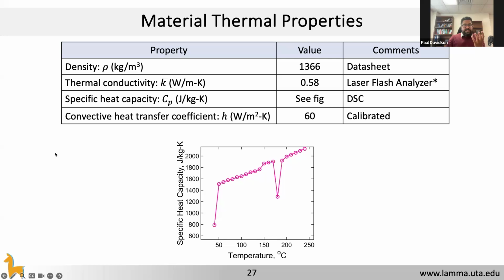So we first measured the material properties of the tape itself. We got the density from the data sheet. We did a thermal conductivity test using a laser flash analyzer. We did specific heat capacity using DSC. There were some outliers which we ignored. Then the main challenge is getting the convective heat transfer coefficient.